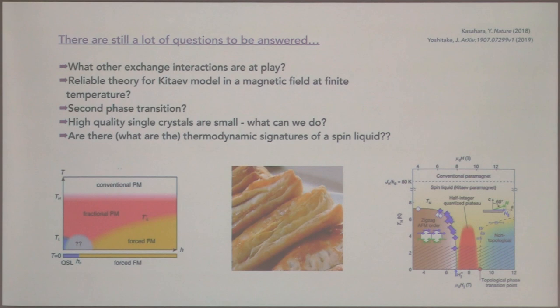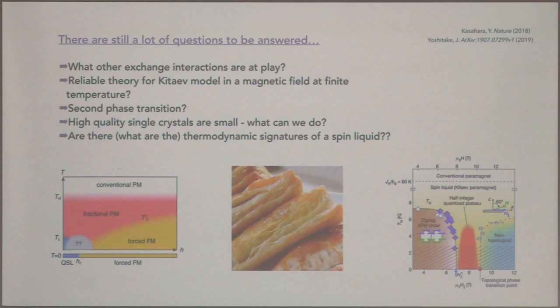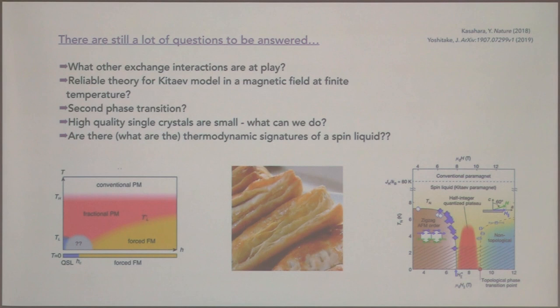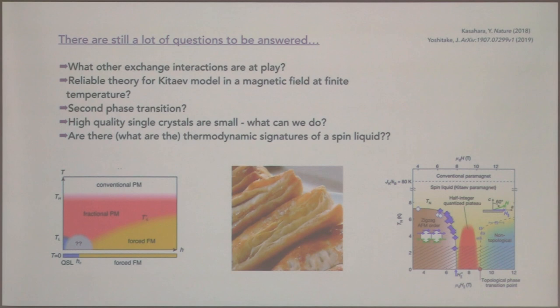The crystals are extremely difficult to work with — they're very much like a pastry. Because of their weak van der Waals coupling, if you try to pick them up or move them around with even one fiber of a toothpick, they start to flake apart. Apparently, they're starting to realize you can anneal these crystals for several months to get much bigger crystals along the C axis. For quite a while it was difficult experimentally to figure out what's going on, with many people reporting several magnetic transitions. It seems that if you look at smaller crystals where stacking faults are less of an issue, those multiple transitions near the antiferromagnetic phase boundary are not so much of an issue anymore.